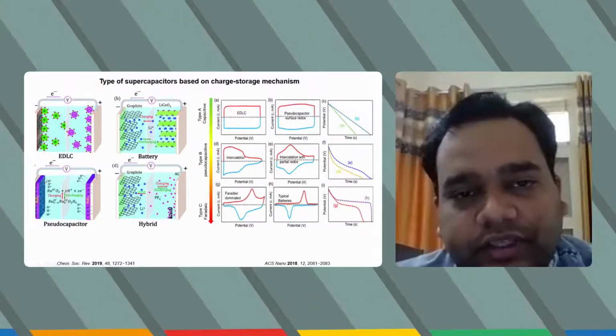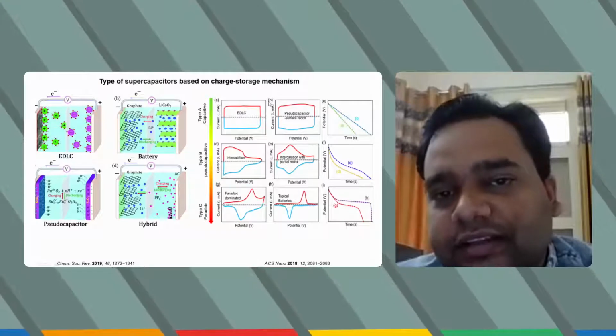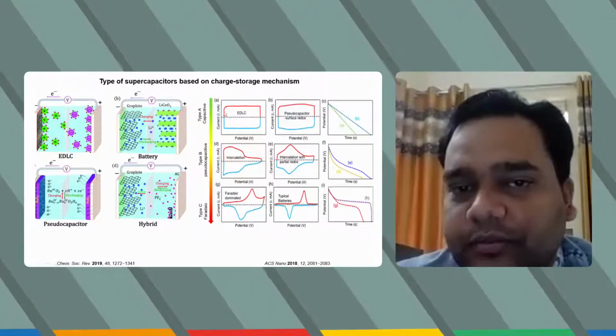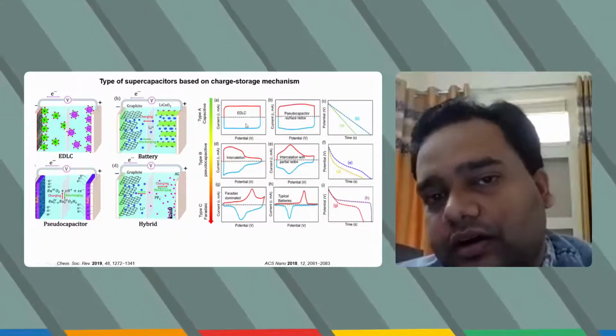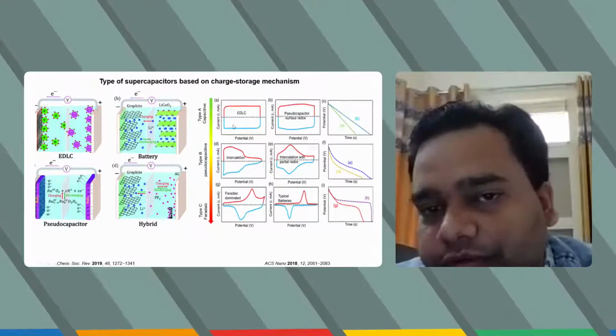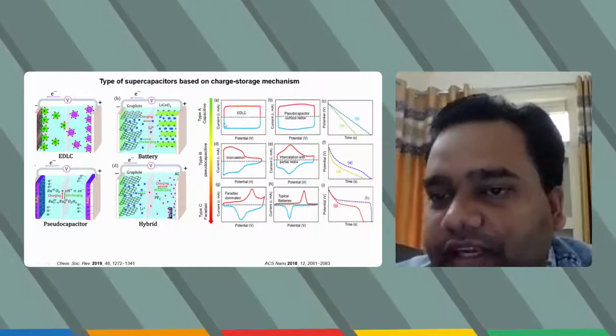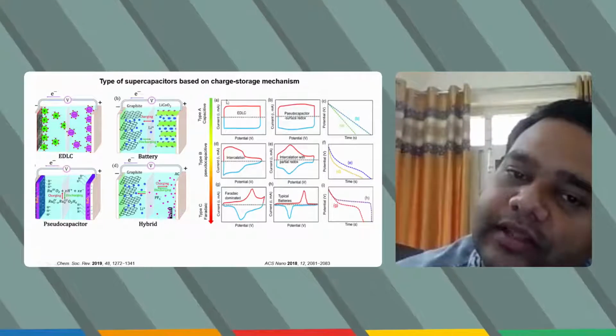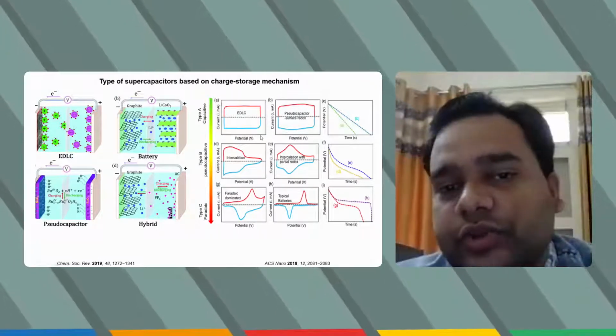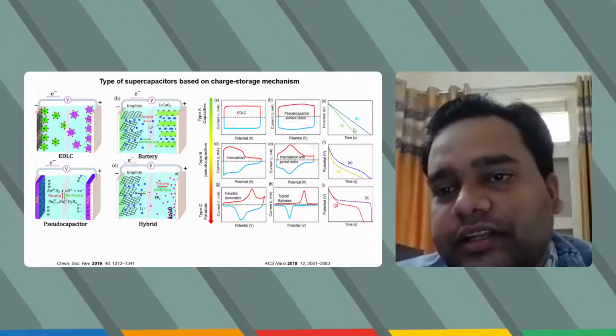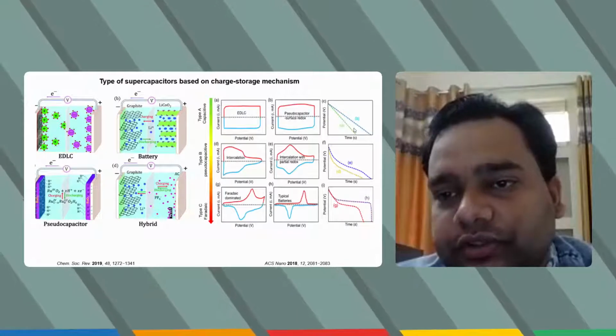So as we see in EDLC type of capacitors, you observe ideal capacitive behavior in terms of a rectangular CV shape, cyclic voltammetry. So you get one curve between current and potential, and you get a linear charge discharge curve, as you can see from this figure C.